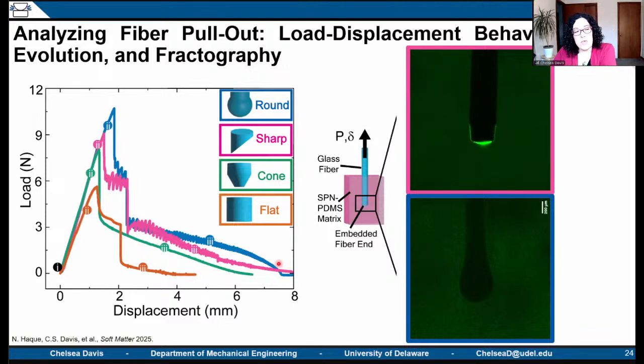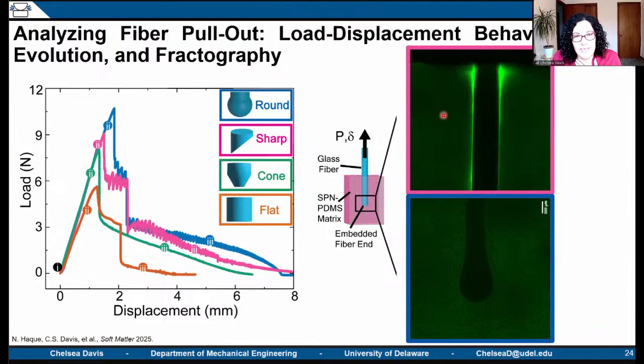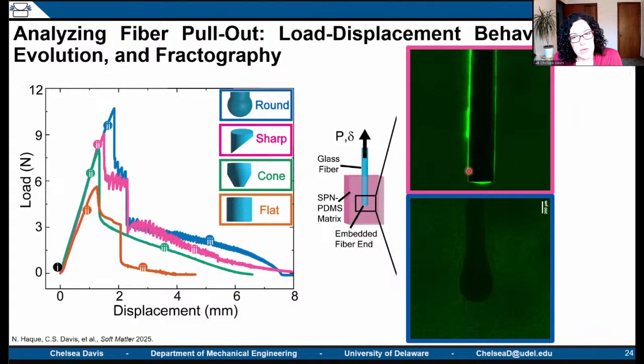So what those corresponded to for the flat, oh, I've got my colors wrong. I did this wrong. This is the flat geometry. This should correspond to this orange case. I wanted to show you the extremes. So this is the flat geometry where you can see that we have very intense activation, but in a very specific way, where we are only observing mechanophore activation due to sliding or the very high forces that are occurring right at the edge. And we only saw a tiny bit of activation right at the edge.